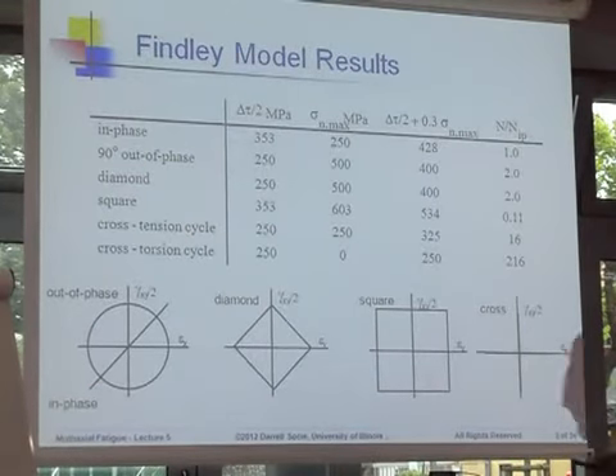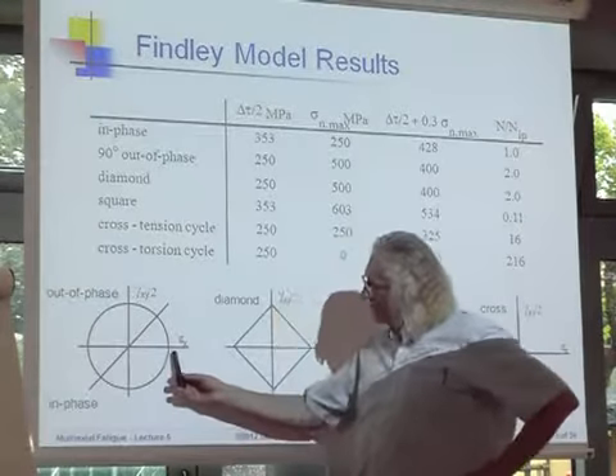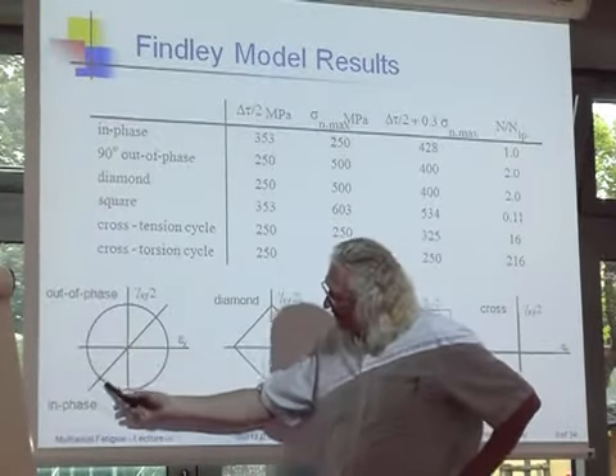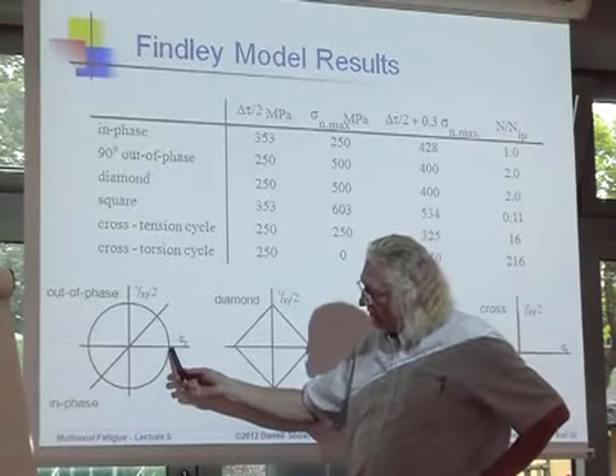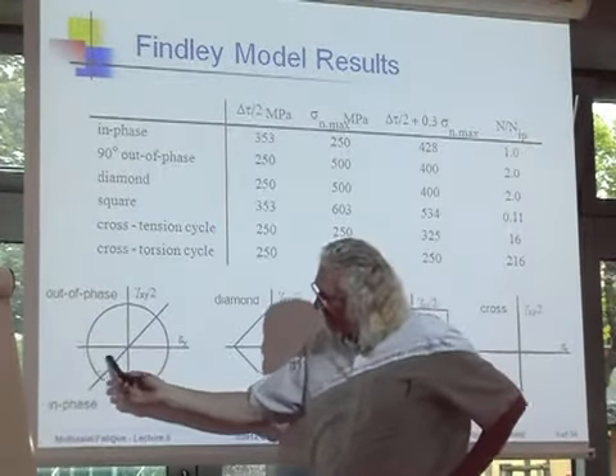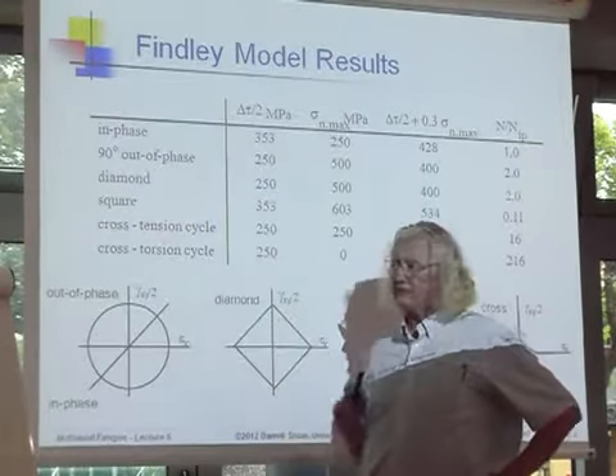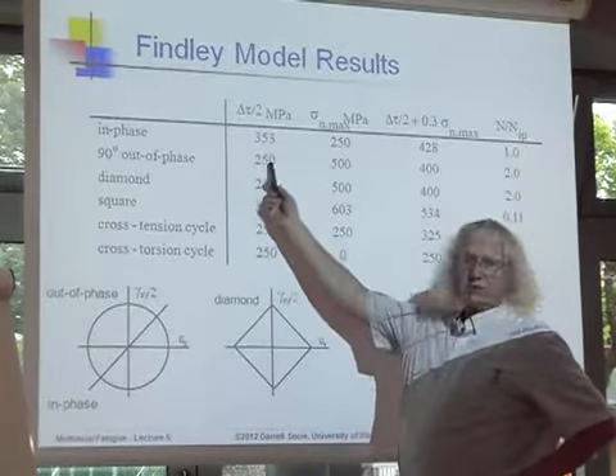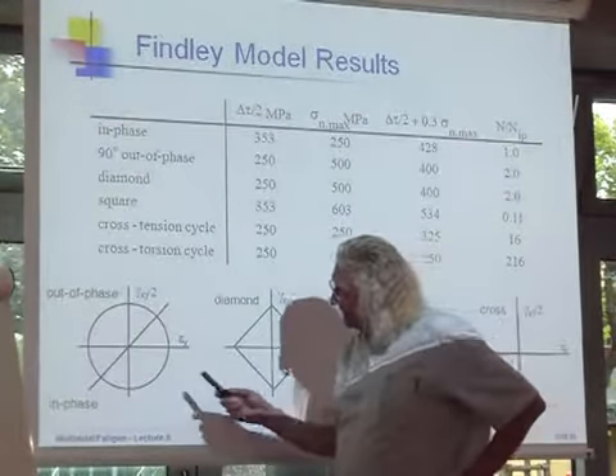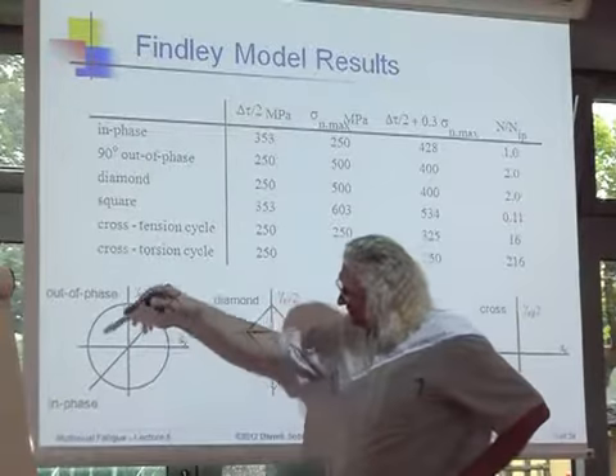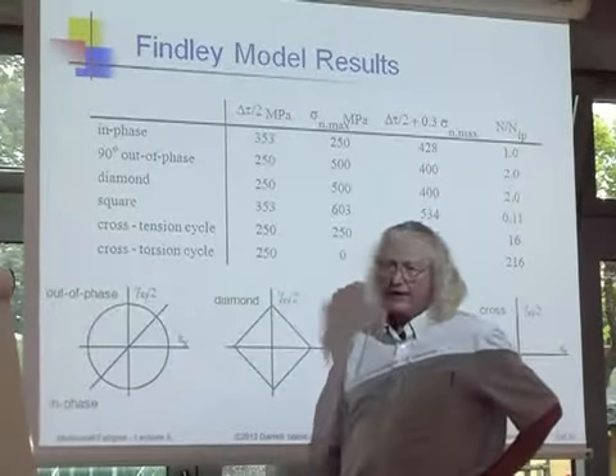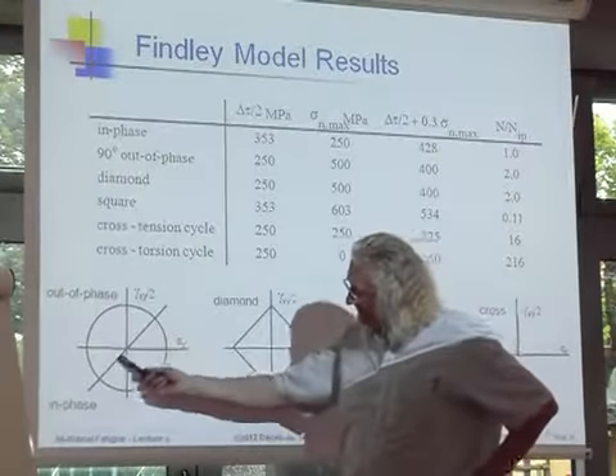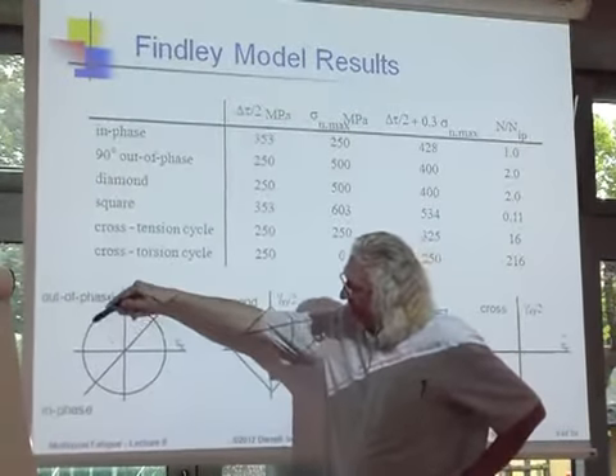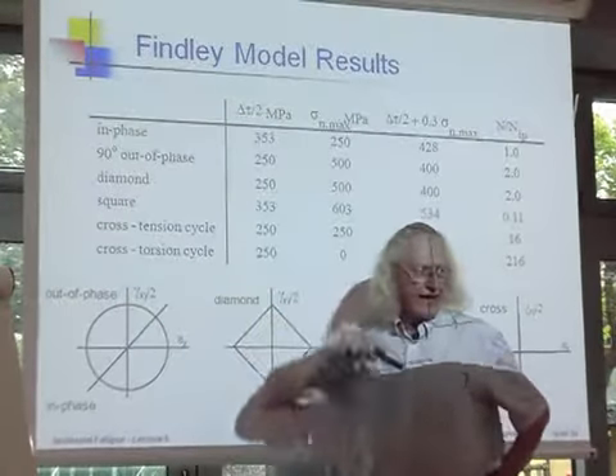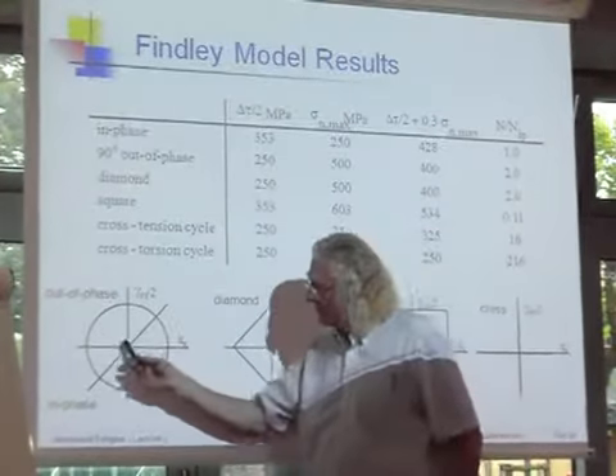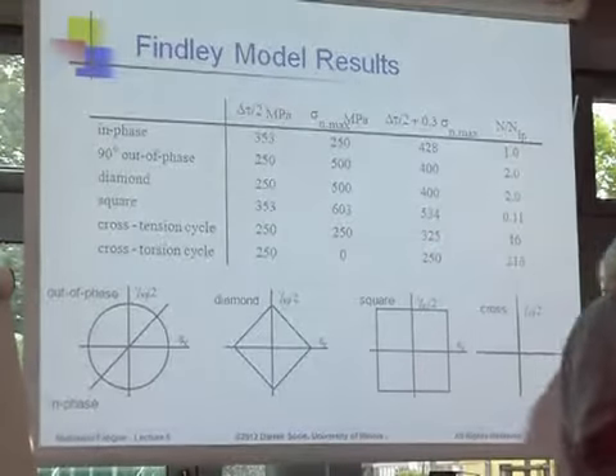And then I look at the 90-degree out-of-phase test. So when I look at this, I immediately say, oh, the magnitude of the range must be smaller. Okay? True. The magnitude of the range is smaller. But in addition to the shear stress, there's now also a big normal stress. And you can think about the normal stress, that if this is the shear plane, the normal stress is related to the distance that's perpendicular to that. I can say, look, wow, that's a big circle. So this will have a big normal stress.